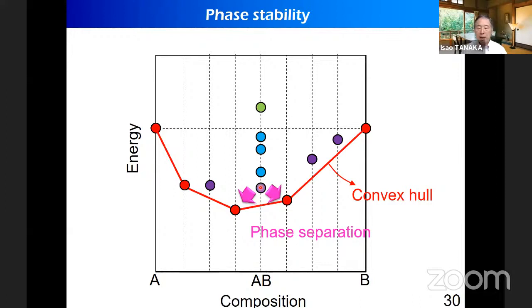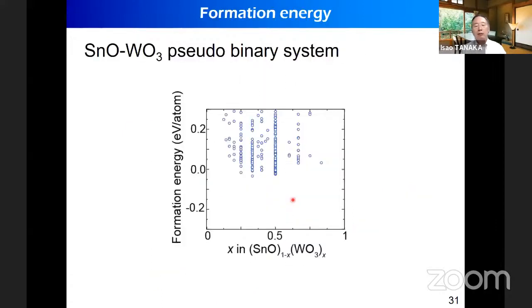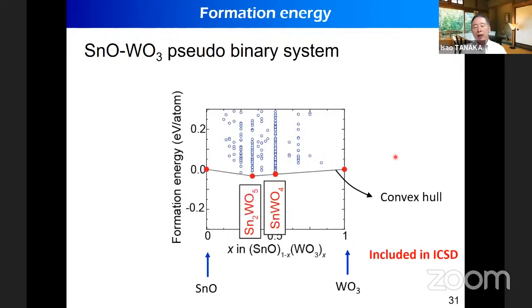It may be subjected to the phase separation to this 3 to 5, 5 to 3 compound. So we need to examine the phase stability. It is a quite lengthy calculation, but is doable. So those all plots correspond to each DFT calculation. And we can draw the convex hull in this way to find this 215, 114 compound on the convex hull.